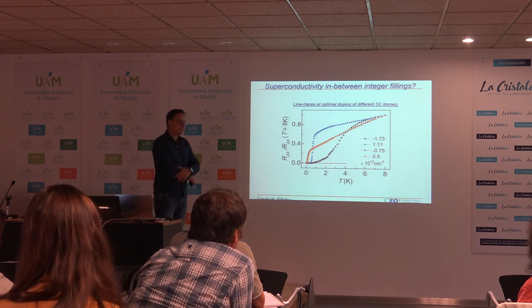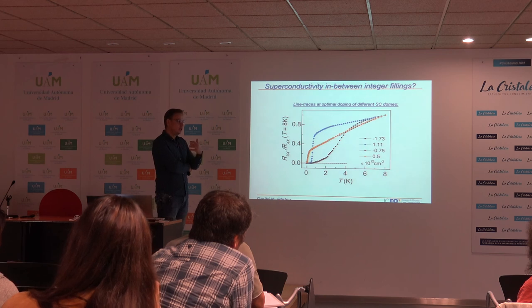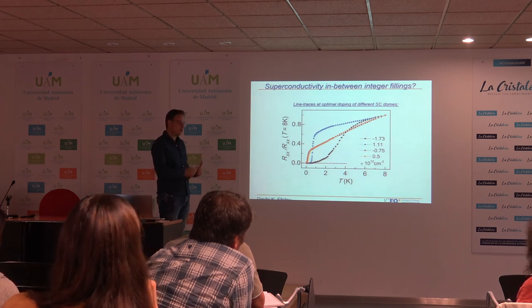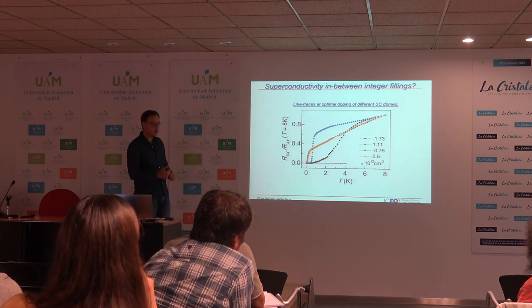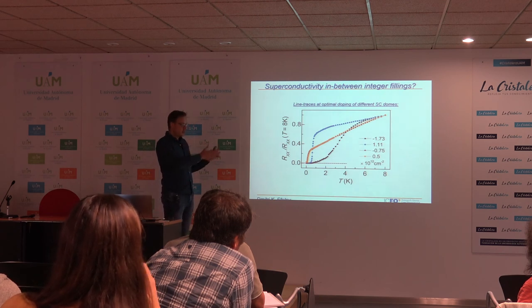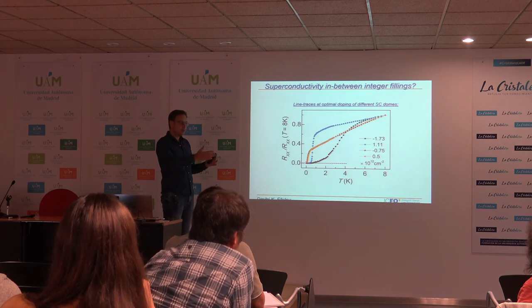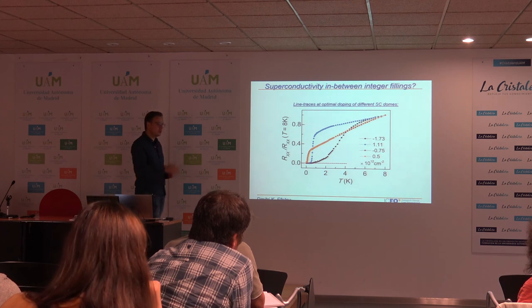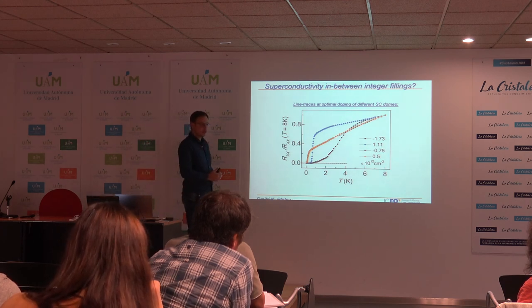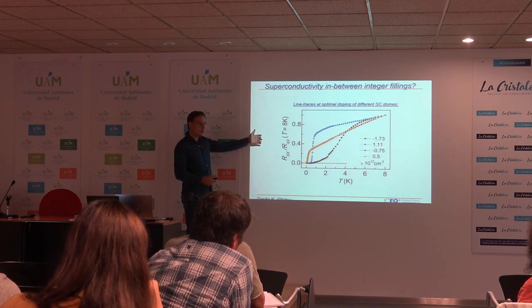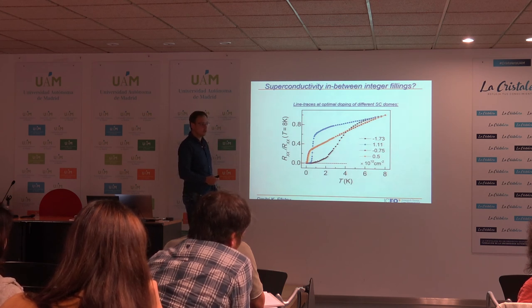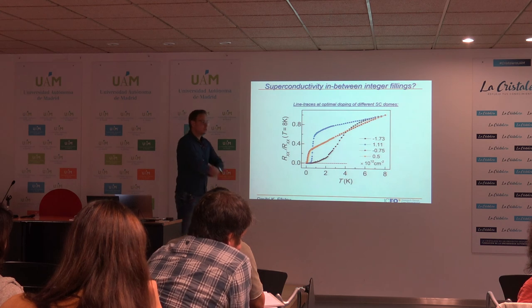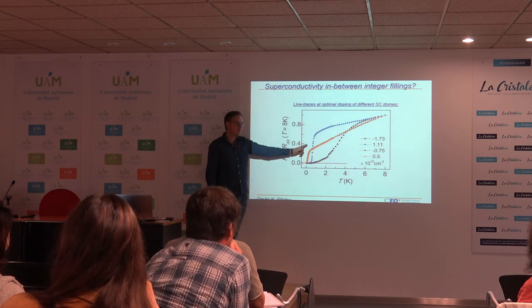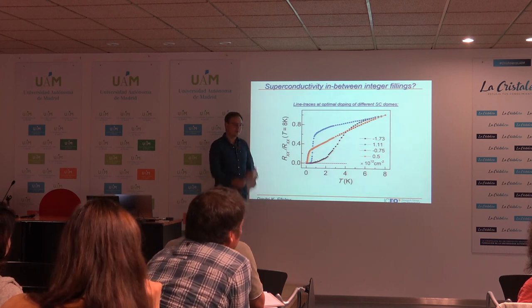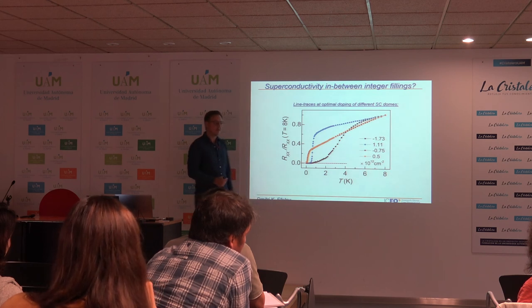Of course we don't know, but if you think that these are correlated states which give rise to the superconductivity, going with this picture of unconventional superconductivity arising from a Mott-like or correlated insulator state, then since all of these states could have different symmetries, they could have different spin degrees of freedom, different valley degrees of freedom. So you could also think that these are different interactions which give rise to the superconductors. You don't expect the superconductor that lives close to the quarter-filling state to be necessarily the same as the one which lives close to the filling factor 2 state, for half filling. So this is one of the explanations we give. On the other hand, Tc is also much lower here, so the transition should also be broader if you have a much lower Tc. That would be just a conventional sort of explanation, I think.